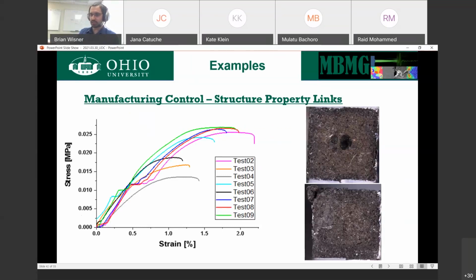This particular one is coal particles embedded in HDPE. The top and the bottom show you the result of injection molding this material. The top sample corresponds to these low load curves. The bottom sample corresponds to the high load curves. Ultimately, we like the high load curves.